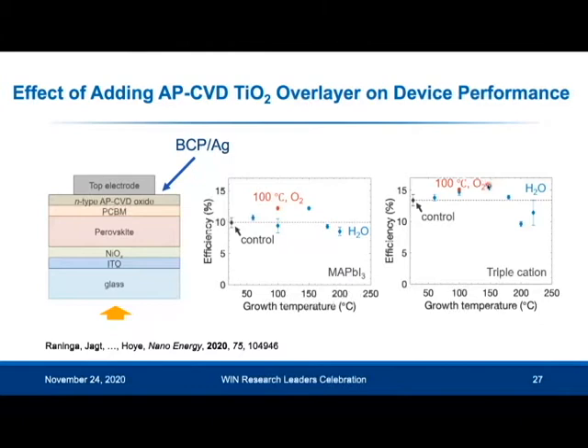And you can see that with these oxide overlayers, not only are we avoiding decreasing the efficiency, we actually achieve an improvement in the efficiency. And the reason for that is because the spin-coated PCBM layer has pinholes in it, which lead to a little bit of shunting, whereas the APCVD TiO2, even if it's only 7 nanometers thick, is still dense and pinhole-free and can block these shunt pathways. So we can improve the fill factors and achieve these improvements in the efficiency.